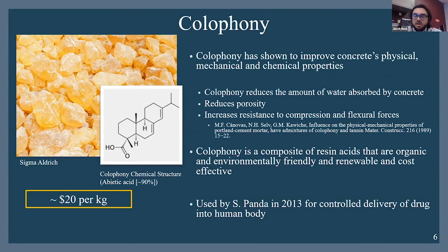To encapsulate these corrosion inhibitors, we wanted to use an environmentally friendly shell material. So in previous research by Panda et al., the colophony or pine resin has been used for delivery of drugs in a simulated human body environment, and research by Canovas et al. has shown that colophony pine resin itself can actually increase the mechanical properties of the concrete in terms of its compression and flexural forces. Colophony is formed of many different resin acids, but is mostly composed of abietic acid, shown here in this inset, about 90%, and it's very cost effective. So it's a good vehicle for our corrosion inhibitors in our reinforced concrete.